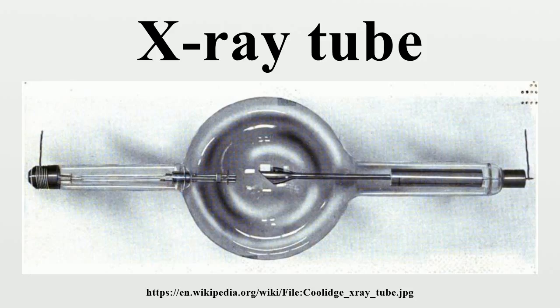In the case with a 10 micrometers electron beam focus, a metal jet anode microfocus X-ray source may operate at 30 to 60 W. The major benefit of the increased power density level for the metal jet X-ray tube is the possibility to operate with a smaller focal spot, say 5 micrometers, to increase image resolution and at the same time acquire the image faster, since the power is higher than for solid anode tubes with 10 micrometers focal spots.